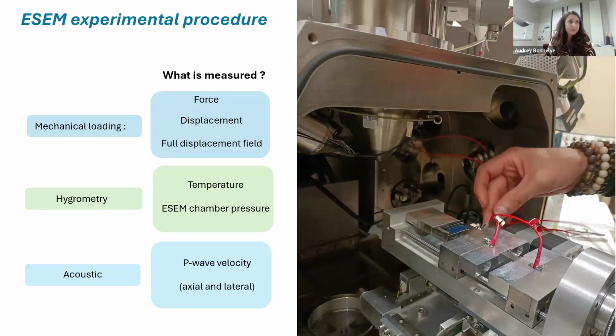So what do we measure? First we are loading a sample. So this is a machine, but I will show more slides and more description of the loading apparatus. We are uniaxially loading a sample, and we are doing that directly inside of an SEM, which is an environmental SEM. And we are measuring the force, the displacement, and the full displacement field thanks to digital image correlation. We're controlling the temperature and the hygrometry inside of the SEM. And in the meantime, we are measuring the evolution of p-wave velocity, both axially and laterally, with respect to our sample.